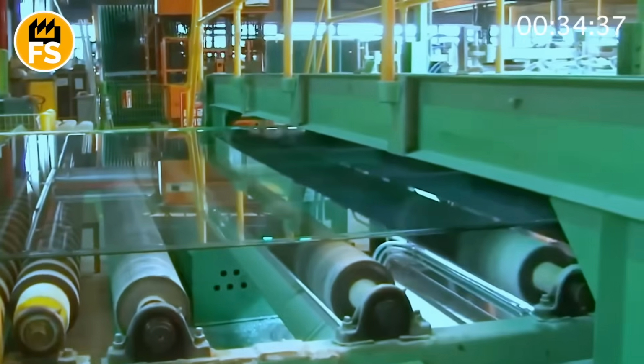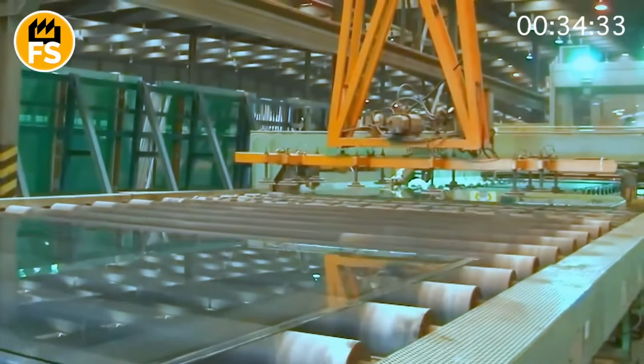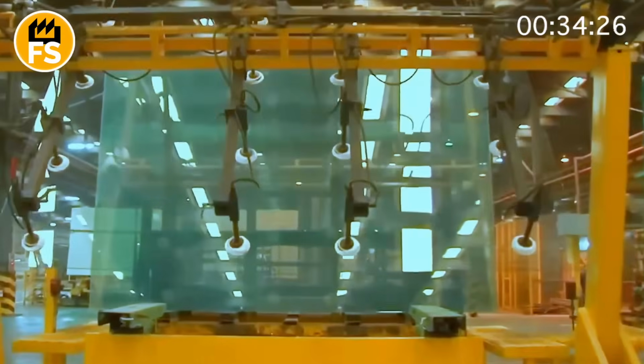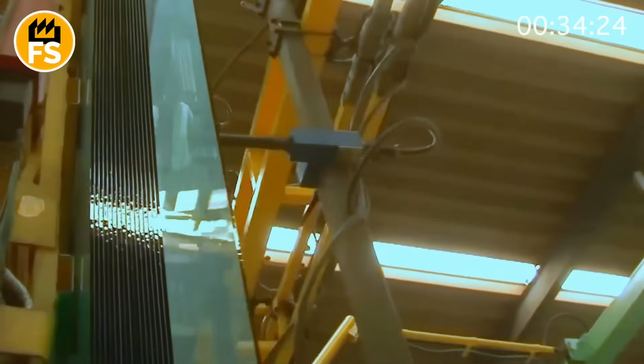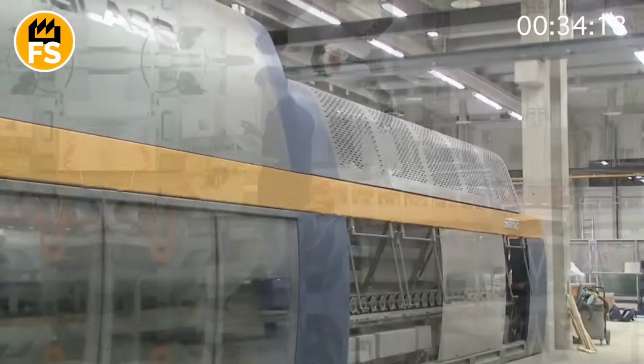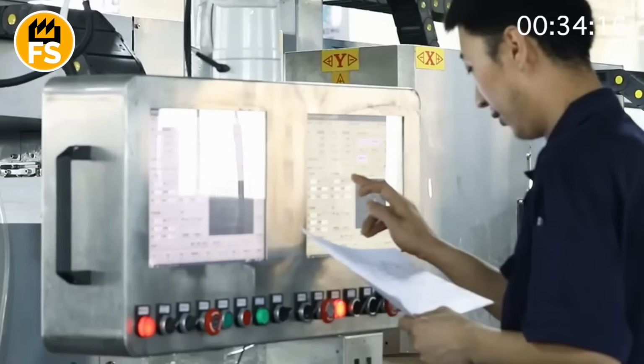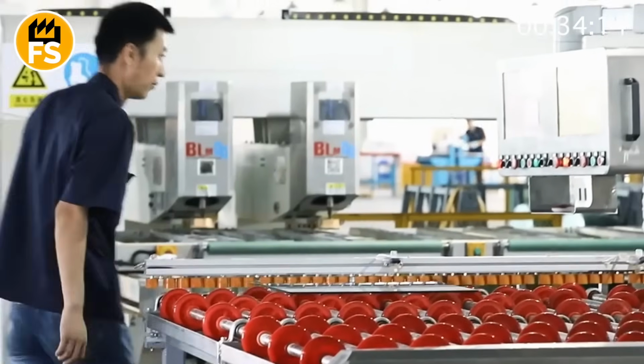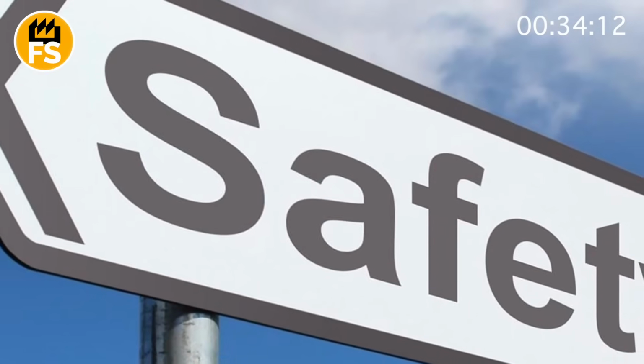It is this brilliant internal architecture of stresses that gives the glass its new superpowers. It looks the same, but now it is a completely different material in terms of its properties. Ordinary glass has a bending strength of about 6,000 pounds per square inch. Tempered glass easily withstands over 24,000 psi, making it 4 to 5 times stronger. But its main advantage is safety.